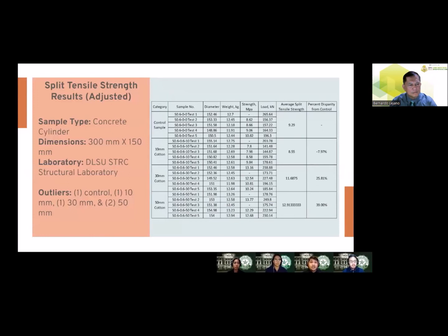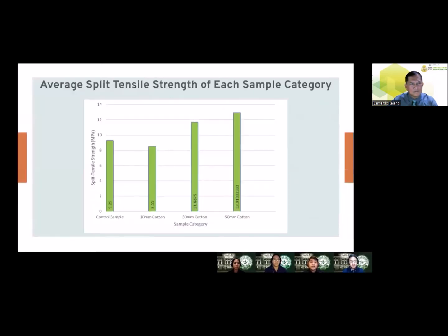Outliers were taken out and the average split tensile strength was adjusted accordingly. It is seen that the adjusted strengths are 9.29, 8.55, 11.69, and 12.91 MPa respectively from the control to the 50 mm. To further visualize the differences in strength, here's a figure that shows a comparison between the four cases. The results show that the use of 50 mm cotton fibers yielded the highest split tensile strength, while the use of 10 mm yielded the lowest.